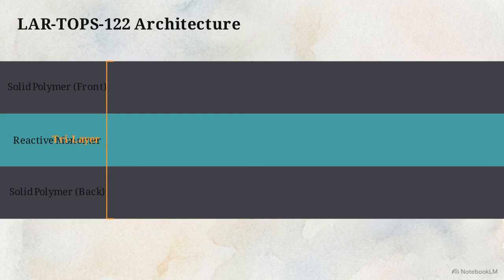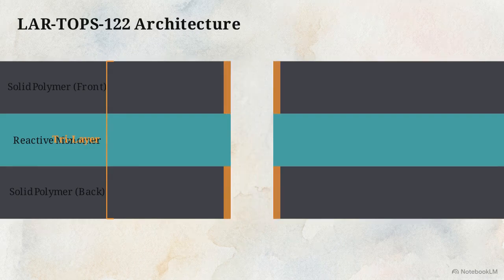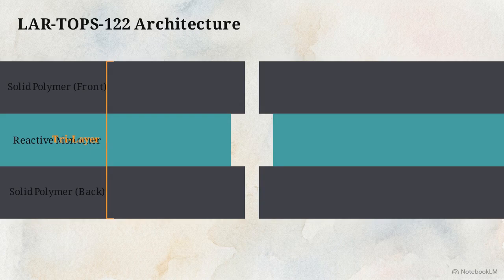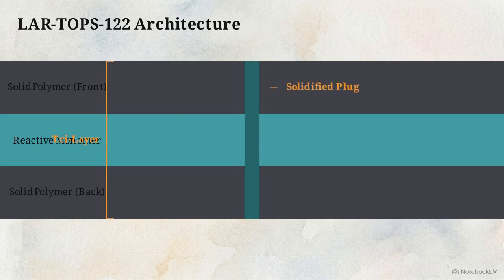The LAR-TOPS 122 architecture utilizes a tri-layer design. Rather than relying on an external heating element, it harnesses the extreme friction heat generated by the projectile impact itself to trigger localized polymer melt elasticity in the solid front and back layers, causing the puncture hole to rapidly snap back and close. This is immediately followed by a secondary extrinsic mechanism. Sandwiched in the middle layer is a viscous reactive liquid monomer. This fluid flows into the remaining void and instantly solidifies upon exposure to ambient atomic oxygen.